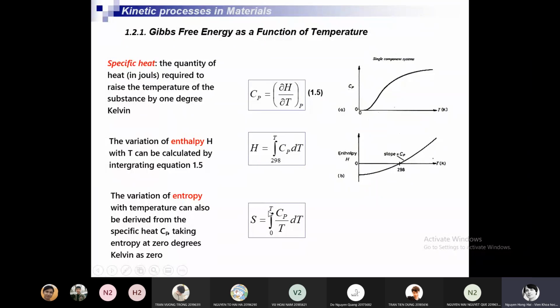From 0 Kelvin to the temperature of interest, the integral of the ratio Cp over T dT. And we have this curve, the entropy curve versus temperature. The variation of specific heat, enthalpy, and entropy with temperature, on the axis we always have temperature. So we have very important thermodynamic terms such as specific heat, enthalpy, and entropy. You can calculate them and plot the graphic versus temperature.